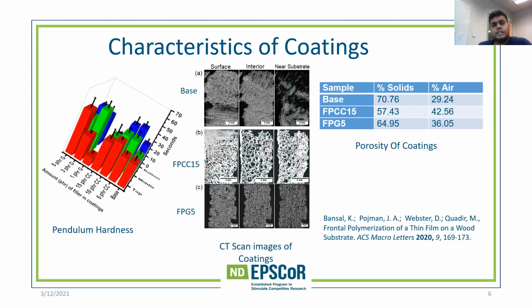Next, we studied the properties of the coatings, and on the left-hand side is shown the pendulum hardness, how hard the coatings were. For some of the coatings, I was not able to get the hardness because the surface was uneven, but most of the coatings were in the range of 30 to 40 seconds and moderate hardness.